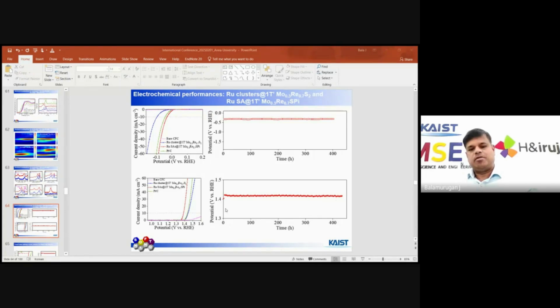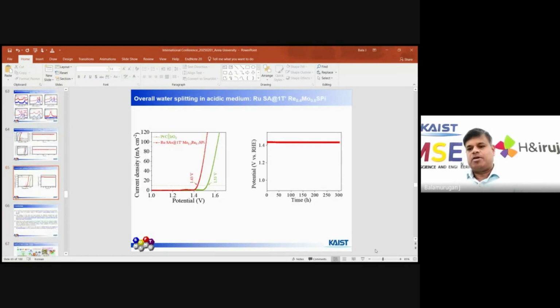HER and OER performance. And finally, we measured the water splitting performance. Water splitting, compared to the commercial catalysts like platinum and iridium, the ruthenium catalyst gets 1.43 volts. But in the case of platinum, it is maybe around 1.53 volts. But this work was all done in acidic media, not in basic media.